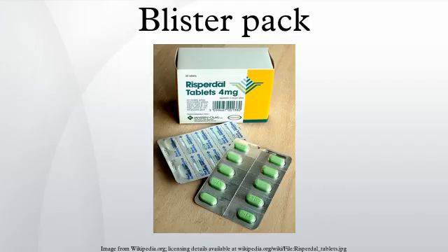The most basic material for the forming web is polyvinyl chloride (PVC). The principal advantages of PVC are the low cost and the ease of thermoforming. The main disadvantages are the poor barrier against moisture ingress and oxygen ingress. Moreover, PVC has a negative environmental connotation due to its chlorine content. In blister packaging, the PVC sheet does not contain any plasticizer and is sometimes referred to as rigid PVC. In the absence of plasticizers, PVC blisters offer structural rigidity and physical protection for the pharmaceutical dosage form. The blister cavity must remain accessible by the push-through effect, so the formed web may not be too hard to collapse when pressed upon. For this reason, the PVC sheet thickness is typically chosen between 200 microns and 300 microns depending on the cavity size and shape.